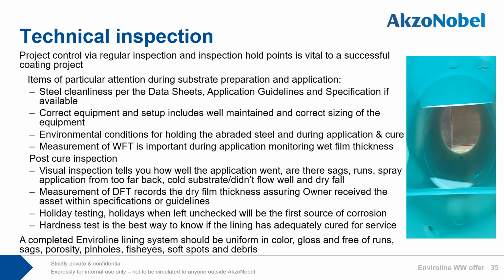Post-cure inspection: a lot can be learned from a visual inspection; it tells you how well the application went. Are there sags, runs, spray application from too far back, cold substrate that didn't flow well, and dry fall? Measurement of DFT does two things: it records the dry film thickness, and shows the owner received the asset within specifications or guidelines. Holiday testing is very important, particularly with aqueous solutions and any immersion environment that has water separation. Holidays, when left unchecked, will be the first source of corrosion, compromising the lining.